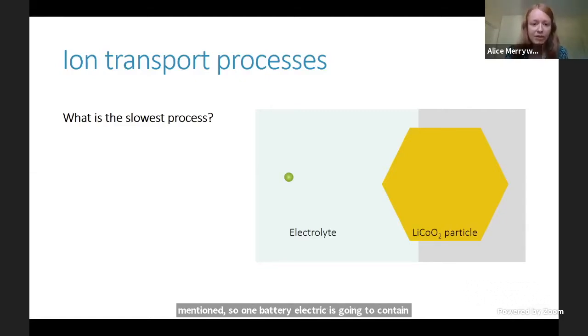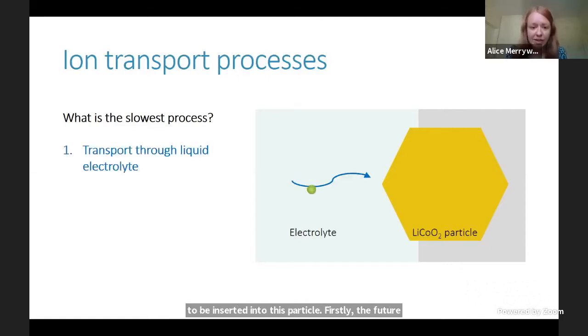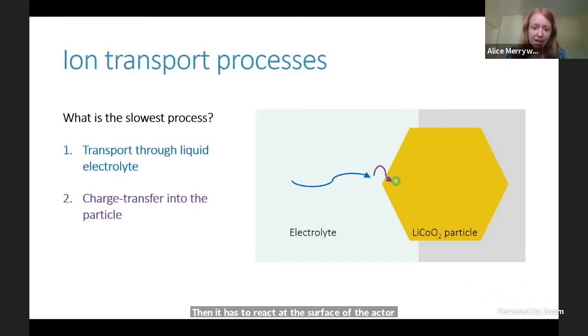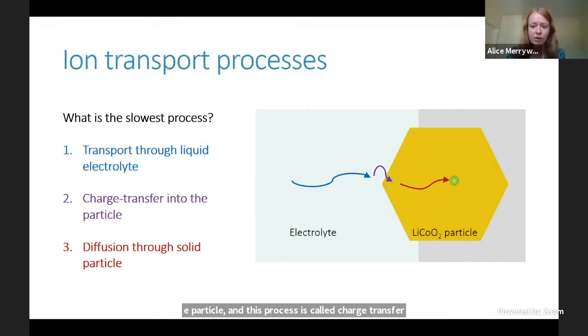In order for a lithium ion, again, a little green fellow there, to be inserted into this particle, firstly, it has to diffuse through that electrolyte salt to get to the particle itself. Then it has to react at the surface of the active particle to cross from that electrolyte into the particle. This process is called charge transfer. And lastly, the inserted ion has to diffuse through that solid particle, away from that surface and into the center. All these processes can occur at different rates, and it can be very difficult to disentangle them and work out which one might be limiting the rate performance of the battery.